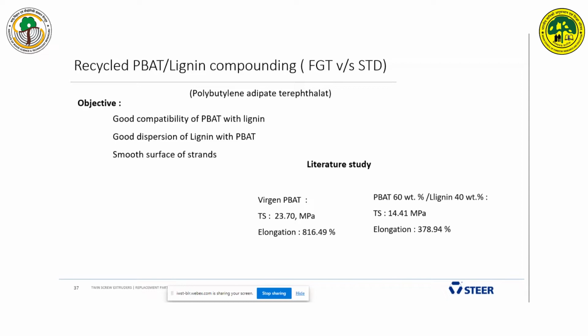This was the literature study we did for a virgin PBAT. The PBAT was 60% and the lignin was 40%. We observed tensile strength 14.4 and elongation 378, and if you see the virgin here, virgin is almost 816 elongation.